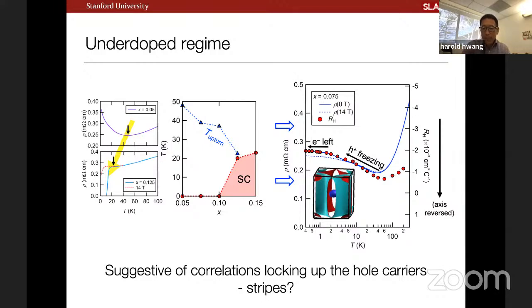So it's a bit of a long story, but if I take a two-band picture and analyze the different possible scenarios, you can find the details in this arXiv paper. We conclude that we're apparently locking up the hole carriers. We can't quite distinguish whether it's a density versus mobility contribution, but that density-mobility product of the Hall channel is clearly freezing out in this problem. And what's left in the transport is electron-like character, we think, coming from these electron pockets. This is very suggestive that perhaps the correlations are locking up the hole carriers. And one candidate, both in the cuprate problem and in our case, might be that these stripe instabilities are what's driving this transport upturn that we see.